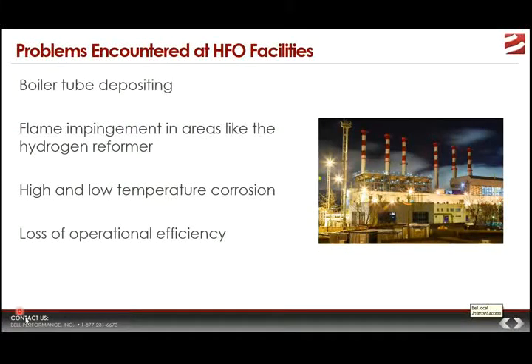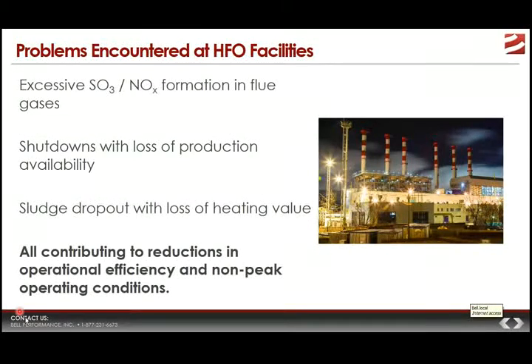So the first thing we have to consider is that HFO, heavy fuel oil, brings inherent problems that stem from its composition and from how it burns. We will touch on each of these in a little detail later, but these problems can be summarized as boiler tube depositing, as you can see on your screen. You can get flame impingement. You can get, of course, high temperature corrosion and low temperature corrosion, and you can get loss of operational efficiency. Excessive emissions like SOx and NOx in the flue gases,